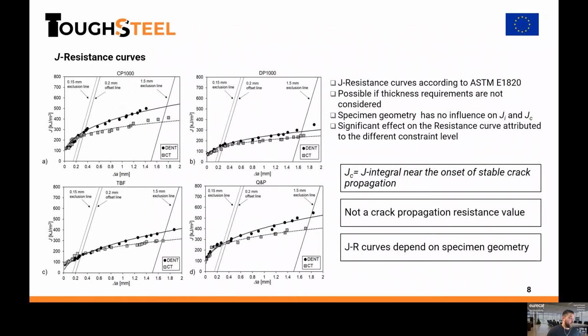We have used it, for example, to evaluate the J-resistance curves of different advanced high strength steels with thicknesses ranging from 1.4 to 1.5 millimeters. Here we have some results for a complex phase, a dual phase, and two third-generation TRIP-assisted steels. What is interesting to note is that this is the resistance curve for two different specimen geometries, shown in the previous slide. The circles correspond to the double edge notch tension specimen, while the squares correspond to the compact tension specimens. One interesting thing to note here is that this J-resistance curve depends on the specimen geometry. Of course, because these J integral values along the resistance curve have an extrinsic contribution to the fracture energy from the plastic work dissipated.